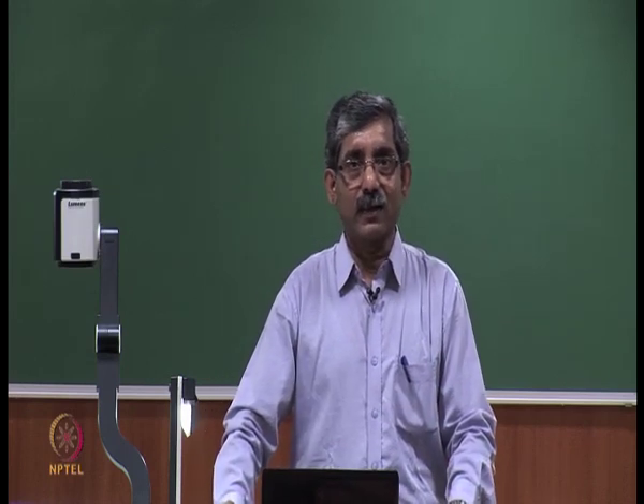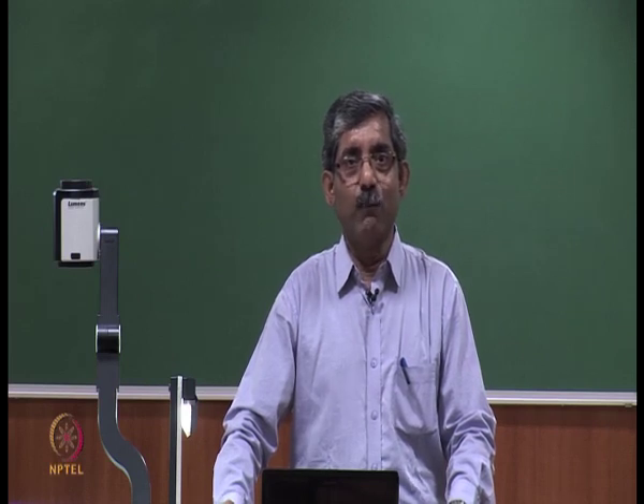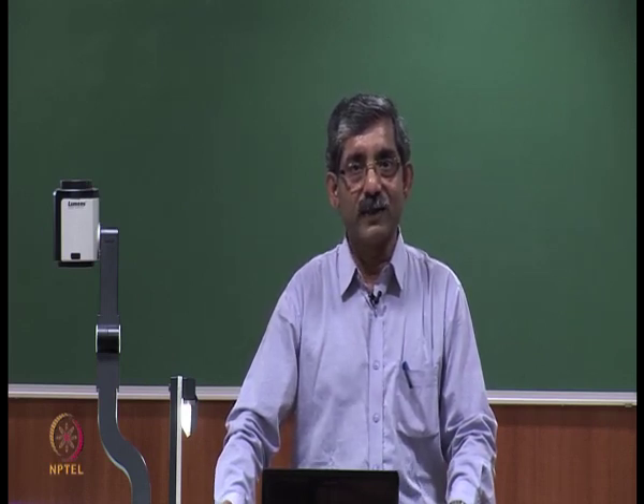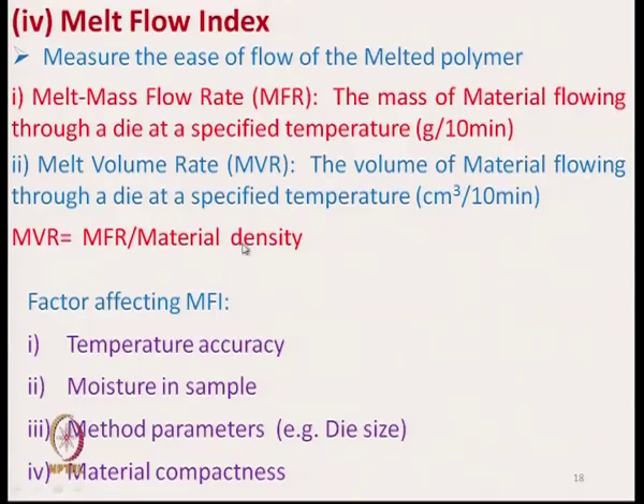Another characteristic is called melt volume rate, MVR. What is melt volume rate? It is the volume of material flowing through a die at a specified temperature, in cubic centimeter per 10 minutes. The relationship is that we can calculate MVR if we know the MFR and material density: MFR divided by material density is the MVR.